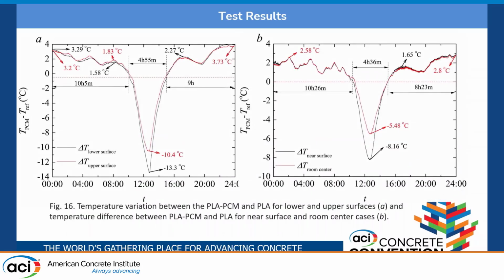So this is even more interesting. We can see the temperature difference between the PCM and the reference specimen. During the daytime, for the surface temperatures, we can obtain up to 13.3 degrees Celsius lower surface temperature. But during the nighttime, we can have around 3 degrees Celsius warmer surface temperature compared to the reference specimen. This shows us that we can significantly reduce the cooling load during the daytime and the heating load during the nighttime or the cold seasons.